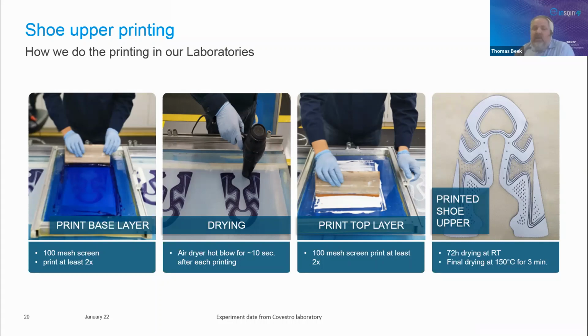We also run trials where, after the printing, we do a direct forced drying without waiting for 3 days, and we can achieve very similar results as with the 3 days drying.